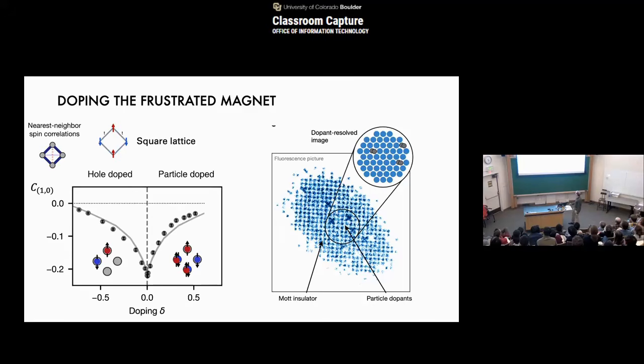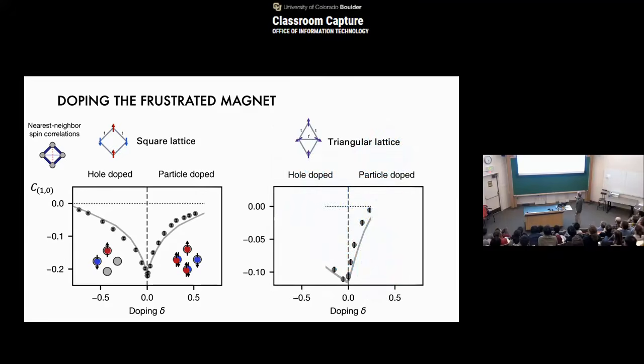When we did this here at half filling, and then we start doping the system with either holes or doublons, we can study how this magnetism changes. And so for a square lattice, famously, you would expect this to be completely symmetric between hole and particle doping, and that's exactly what we found. But if you now go to the triangular geometry, then you see it actually becomes very asymmetric here.